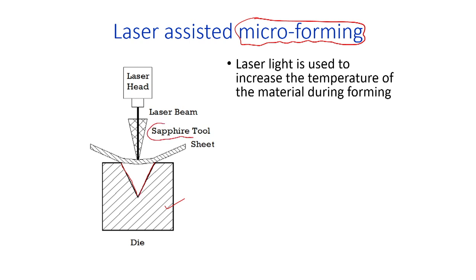We are using a sapphire tool. The sapphire is transparent, and the sapphire tool has been given the required shape with which we want to have the required deformation. Here a triangular shaped sapphire tool is being used, which is transparent, and through this sapphire tool we are applying the laser beam. The laser beam is applied in such a way that it should only heat the work part, not melt it. The laser beam transmits through the sapphire tool and reaches the worksheet, which is between the sapphire tool and the die. As the laser beam is applied, there is a local, controlled heating, and then we apply the sapphire tool to get the required deformation.